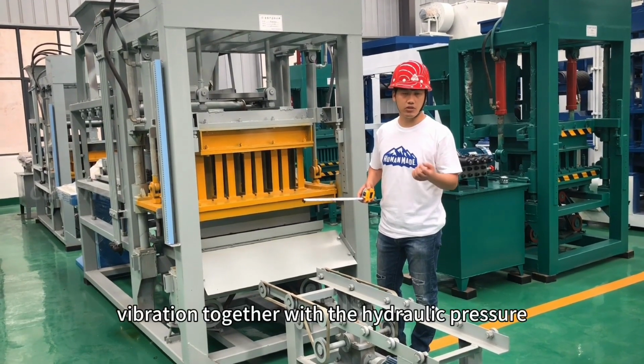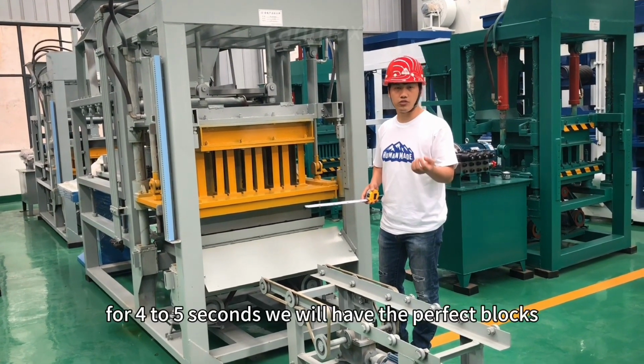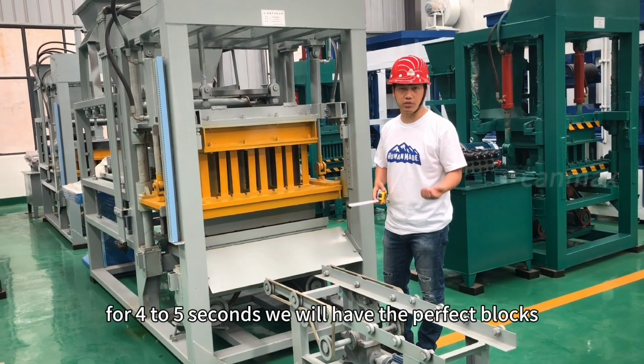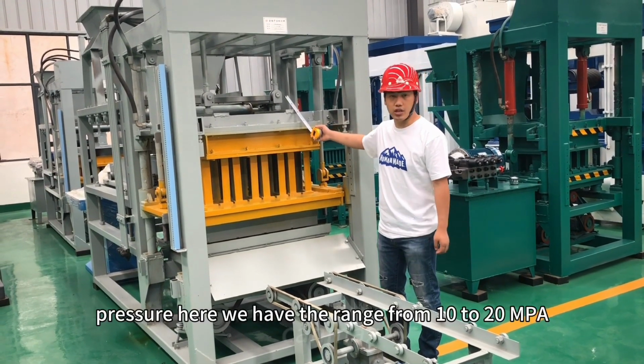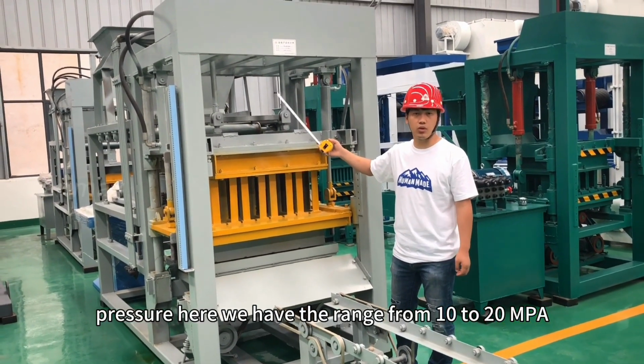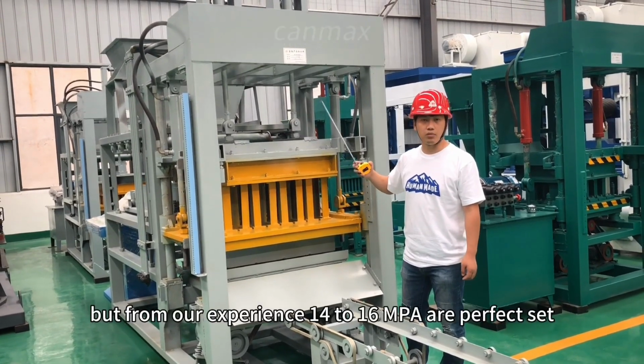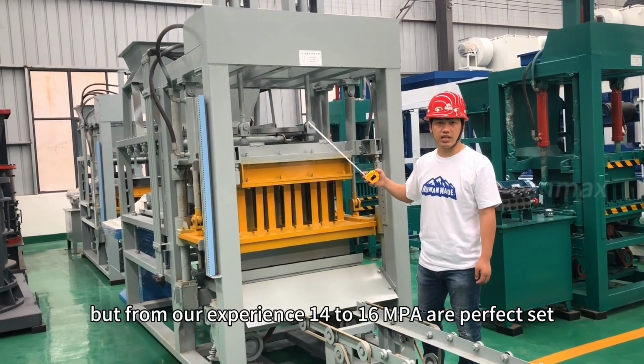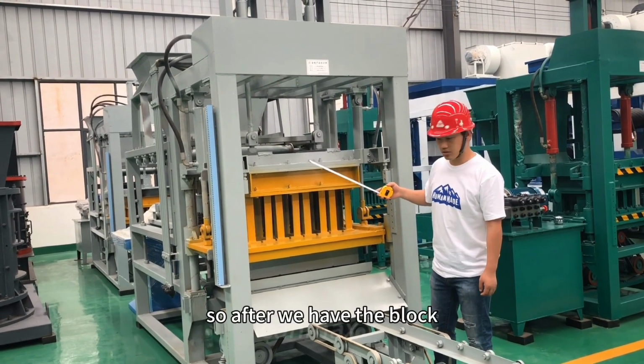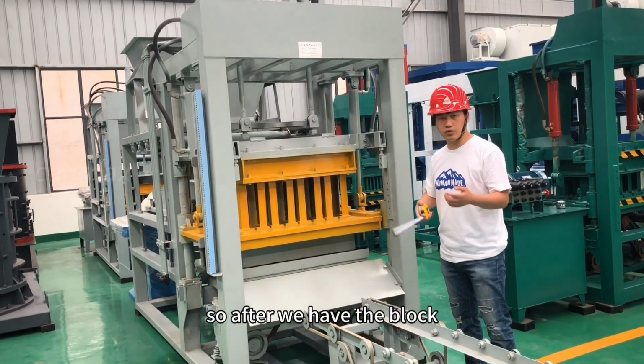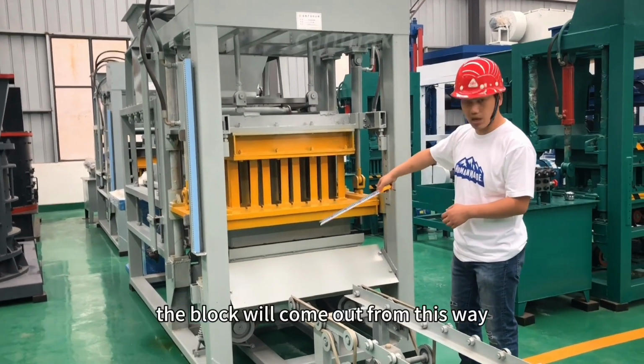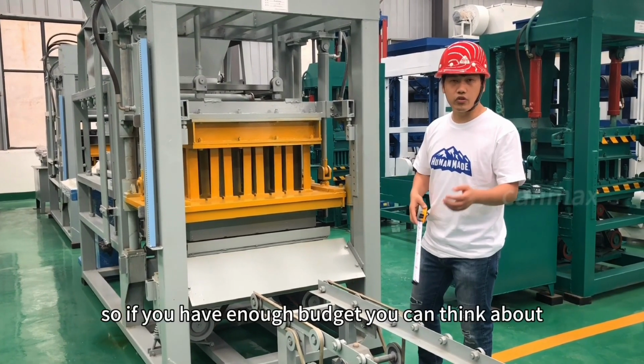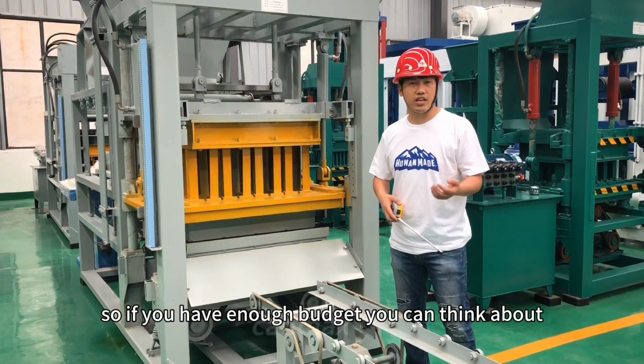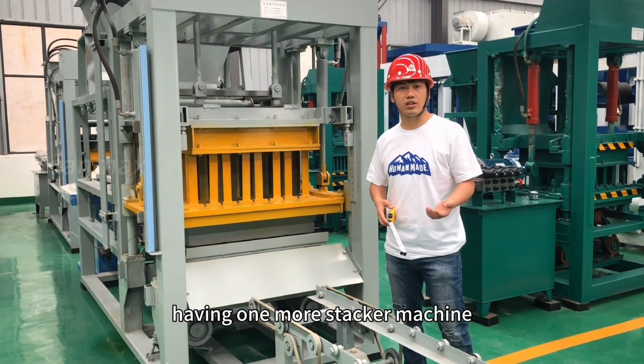Vibration together with the hydraulic pressure for 4 to 5 seconds, and we will have the perfect blocks. About pressure here, we have the range from 10 to 20 MPa. But from our experience, 14 to 16 MPa is the perfect setting. After that, the blocks will come out this way. If you have enough budget, you can think about having one more stacker machine.